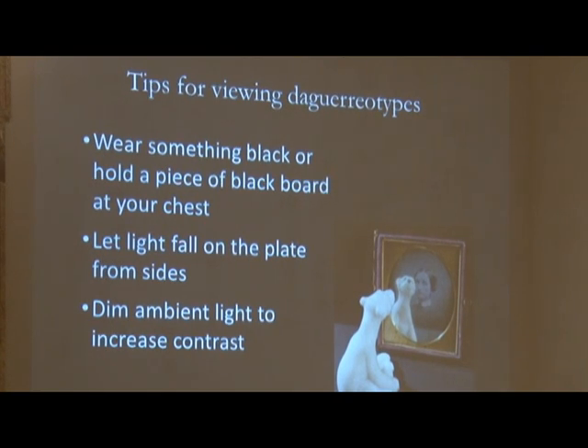Another point is to let the light fall onto the plate from the side. When they prepared the daguerreotype plate, the polishing of the plate was a big part of creating the mirror surface, and it was done by hand in this linear back and forth movement. And they always finished the polishing by going in the horizontal direction. If the image is vertical, a portrait, the polish line is going this way, and if the orientation is landscape, it's going the long way. There's a reason for this.